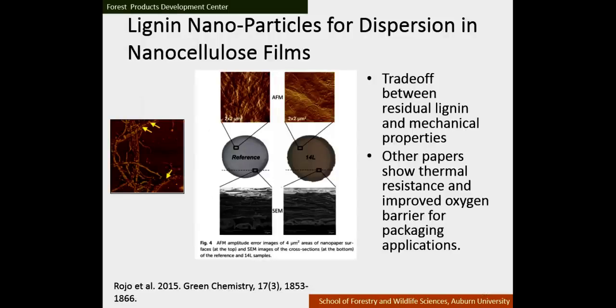And so some interesting work that she's doing that I find very interesting is they're making nanocellulose out of pulp fibers, and those little arrows represent nanolignin particles. So these fibers are covered with nanolignin particles, and in the paper, they say that this can help with dispersion because the lignin keeps the cellulose from aggregating. And so you can disperse the cellulose and hopefully have it equally dispersed within the composite instead of it bunching up in places.